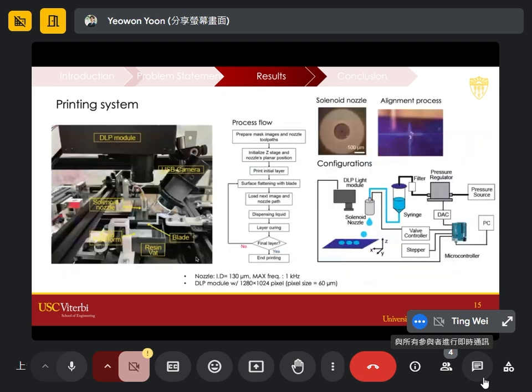So the system is relatively simple. We basically have a customized resin printing setup, and then we had to install another XY plotter that has the solenoid valve nozzle. The nozzle size we are using is about 130 micron, where it can create from 50 to 500 micron size droplets. All this is controlled by a microcontroller and a PC. Then we write G code to run the whole sequence.